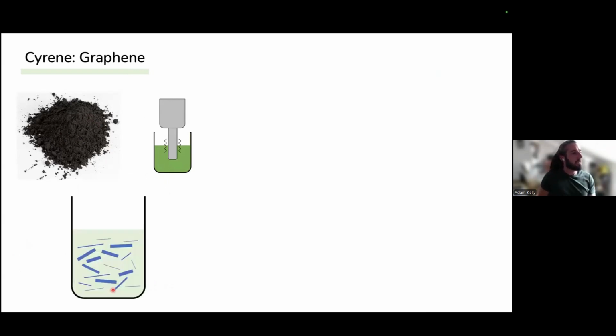So, sonication power of 50 watts, common sonication time of about 6 hours, and initial concentration, sorry, that should be 30 milligrams per milliliter. Now, the problem is when you do this with a bulk powder, you're left with a polydispersion. You have large and small nanosheets all mixed into the same dispersion. And what we want to do is find a way to isolate these out because we want nanosheets of a certain size and certain thickness.